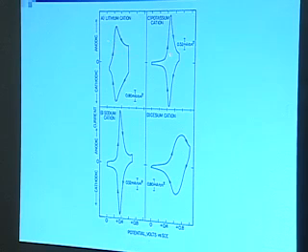So here's a series of cyclic voltammograms for nickel ferricyanide and different nitrate salts: lithium nitrate, potassium, sodium, cesium nitrate. Probably the first thing that jumps out at you is that they have different shapes to them. But what's more important is that the peak potentials are shifting. We start with a very positive peak potential here. It gets very negative here. It gets more positive here, more positive as we drop down the periodic table, and even more positive over there.